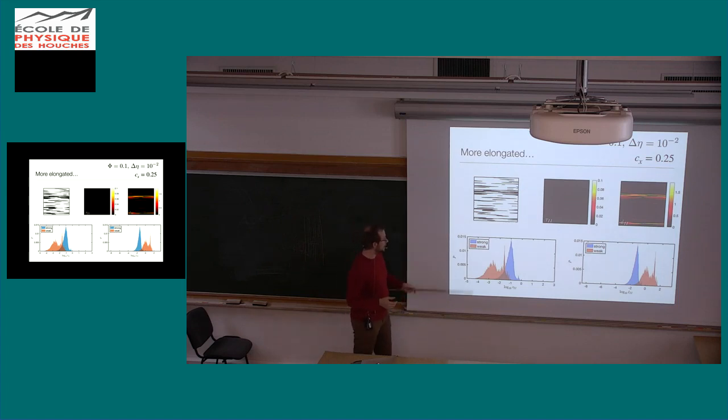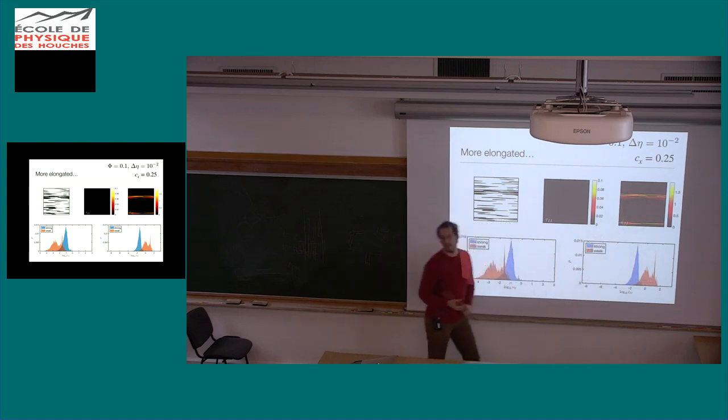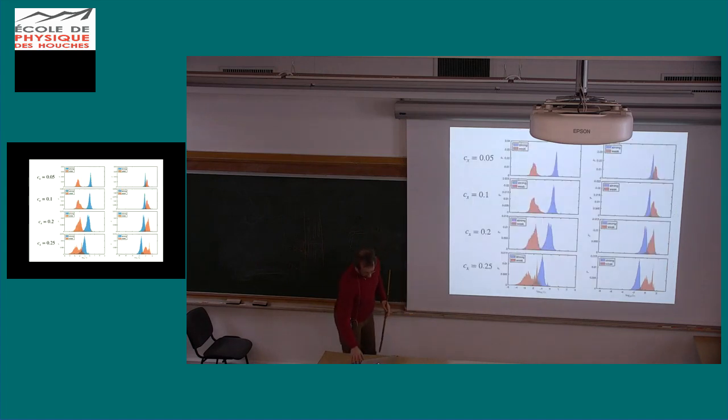What you see here then is that our distributions have changed, especially the one of the weak phase. So you now have this bimodal distribution, with a peak here and here, and this peak corresponds to the high strain in those bands. Not all of the weak inclusions take part, just some of them have this high strain. So this is basically what you see as localization.